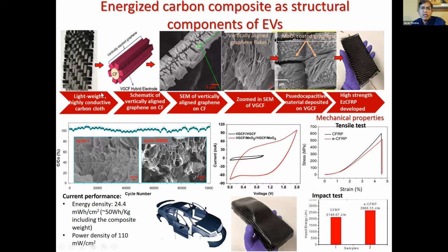But what we have done in this case is we take this type of carbon fiber cloth, and if this is a carbon fiber, then what we do is we attach this type of graphene. As you know, graphene is a two-dimensional material. It has a huge surface area, and remember, your equation: capacitance is directly proportional to the surface area. And here you can see the vertically aligned graphene on this carbon fiber. So what you're getting is a hugely enhanced surface area for the energy storage.